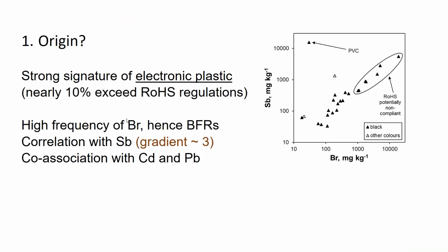Well, if we talk about the origin, one thing that we notice is that the signature of these plastics, especially the black ones, is of electronic waste. In fact, if we were to plot the bromine against the antimony in these beach plastics, we find that the gradient of the relationship is about 1 to 3, or 3 to 1 if you're talking about bromine to antimony. And this is almost exactly the ratio in which bromine and antimony are found in electronic goods. So laptops, mobile phones, TVs, especially the older types of plastics.